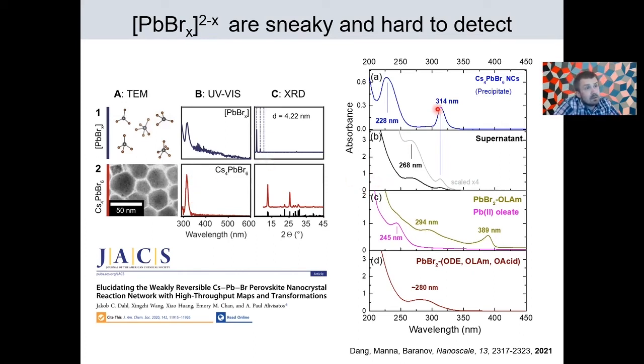In our attempt, we analyzed spectra of isolated nanocrystals and supernatant that contains this species. And then compared it with the spectra of lead bromide dissolved in just oleylamine and lead oleate produced from lead oxide and oleic acid and didn't find a good match. However, when we dissolve lead bromide in the mixture of oleylamine and oleic acid, this peak, even though it is at slightly different wavelength, but shape wise, it matches the one observed in the supernatant, which led us to propose that these lead bromide species are some mixed lead bromide oleate ones.